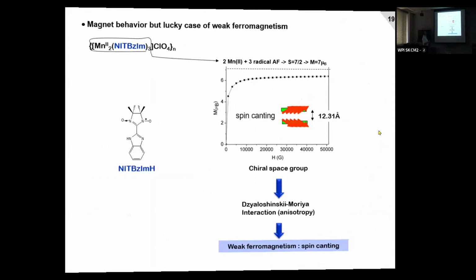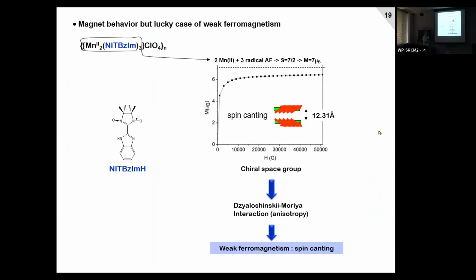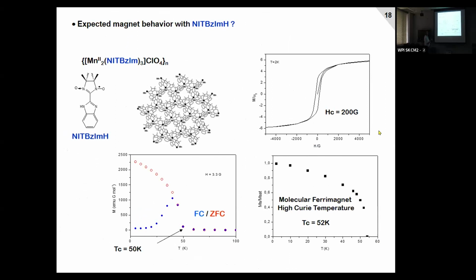So we have done this, and the question is why we have a ferromagnetic order. If you look at the ferromagnetic order, finally you can see that we don't reach saturation. Normally, with two manganese 2 and 3 radicals, I told you that when they are completely anti-ferromagnetically coupled, we expect a spin of 7/2. With a spin of 7/2, you expect the value of 7 for the magnetization. You see that the hysteresis loop finally saturates at 6.